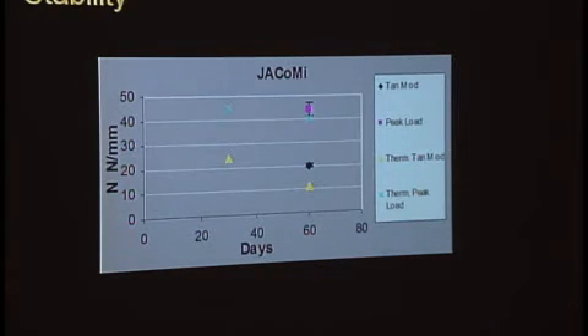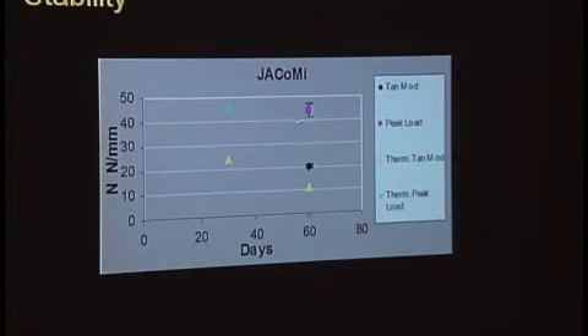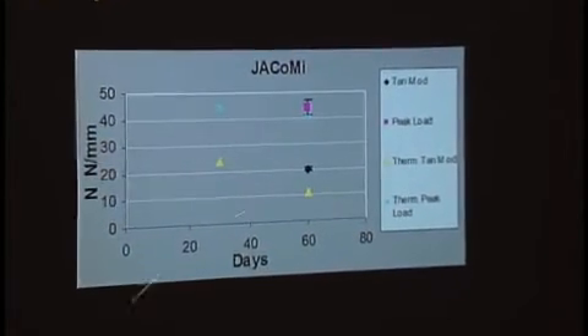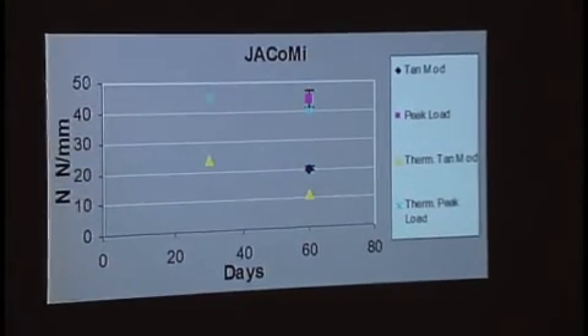And the JACoMi, we only did two lots of times for these because the JACoMi was really too stiff and we didn't carry on the experiments. Compared with all the other data that's also available for JACoMi, it shows it's all kind of stable. There's not many data points to be consistent, but with other data around, it shows it's stable.